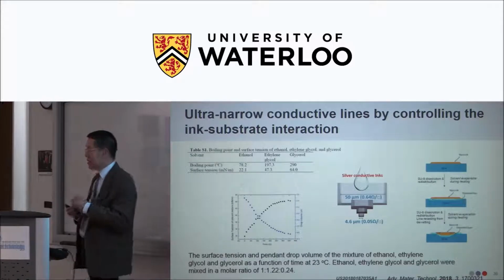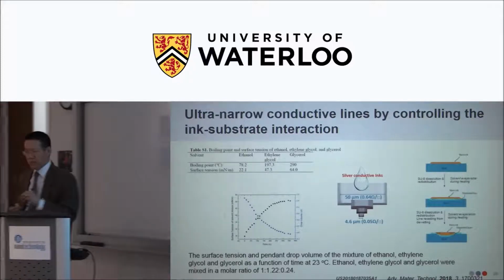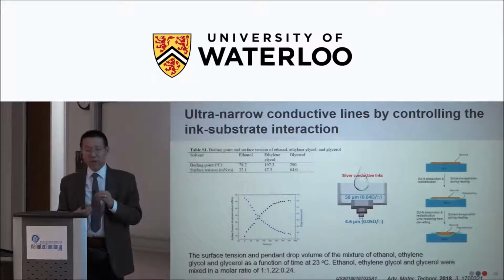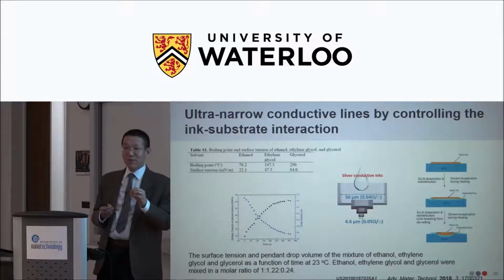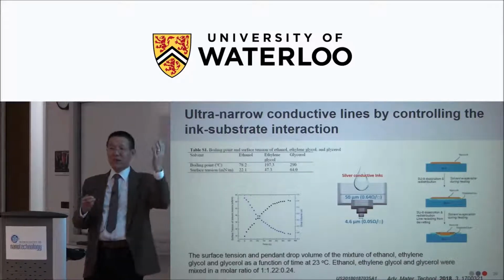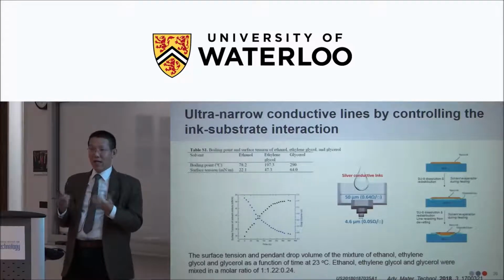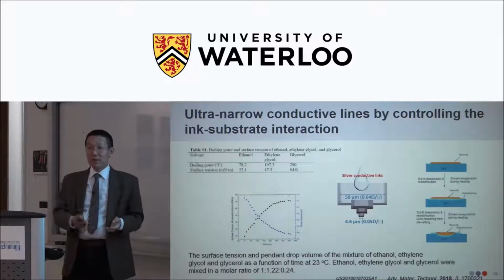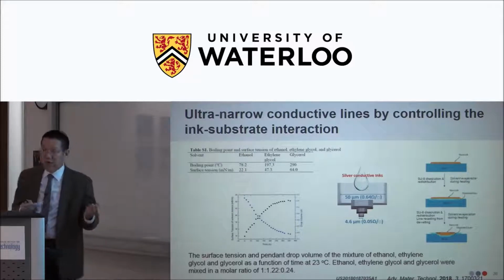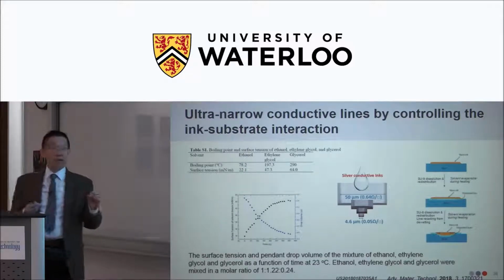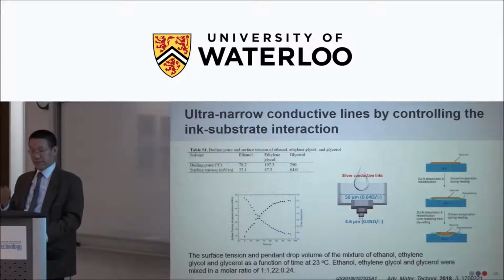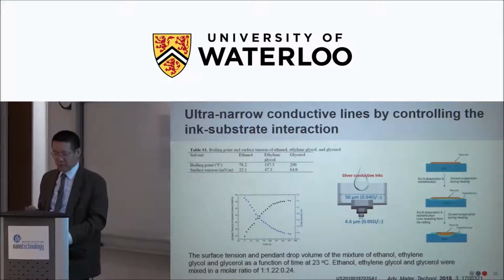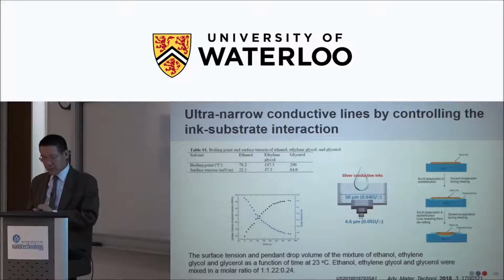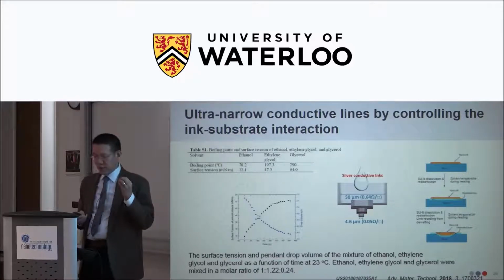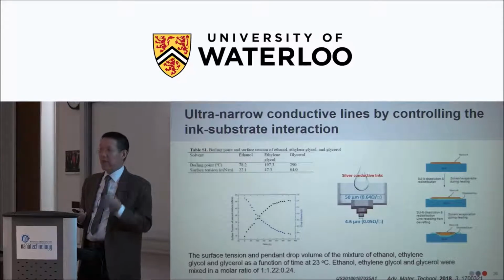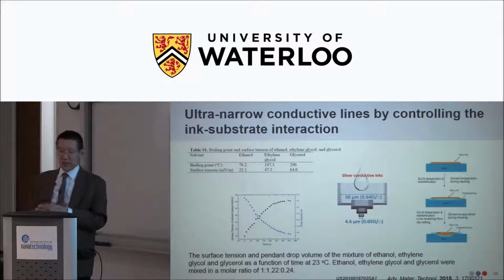And also, because you can get a very thin dielectric layer, we made high capacitors. Normally when you make organic printed capacitors, it is very difficult to get a high value, because you want to avoid the pinholes, right? You want a thinner layer to increase the capacitance, but then the yield is very low. Because the coupling effect made the dielectric dense and pinhole-free, we could make a very high capacitance capacitor. So that's one way we used this coupling effect to make a dense dielectric layer.